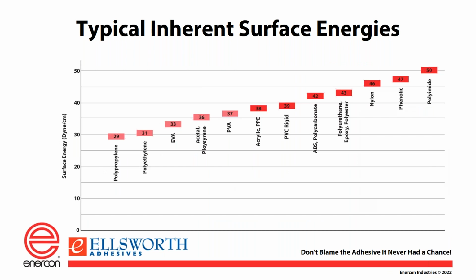This is just a few materials and where they typically start on the dyne level. On the far left, you've got polypropylene, which is around 29, 30 dyne, all the way up to a polyimide that might be at 50 dyne, and then everything else across. But again, this is just to give you an idea of where these materials typically start in their surface energies. And generally, you're going to need a higher number than these in order to get an effective bond. But the only way to really figure that out is to do the testing.